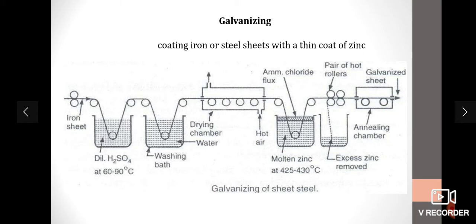For carrying out galvanizing, firstly the iron or steel articles such as sheet, pipe or wire are cleaned by pickling with acid solution for 15 to 20 minutes at 60 to 90 degrees Celsius. After all 5 steps of the surface cleaning process, the article is washed well with water and then dried, and then it is dipped in a bath of molten zinc maintained at 425 to 430 degrees Celsius. The surface of the bath should be covered with ammonium chloride, which acts as a flux to prevent oxide formation of molten zinc. The article is covered with a thin layer of zinc when it is taken out of the bath. It is then passed through a pair of hot rollers which remove any excess zinc and produce a thin film of uniform thickness, and then it undergoes annealing at a temperature of 650 degrees Celsius and is finally cooled slowly. Annealing means heating and then slow cooling.